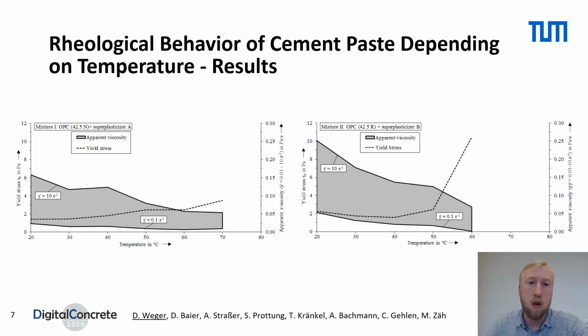The diagrams show the yield stress in dotted lines and the apparent viscosity between a shear rate of 0.1 and 10. The literature mentions these shear rates as the ones appearing during the penetration of cement paste under gravity in the particle bed.